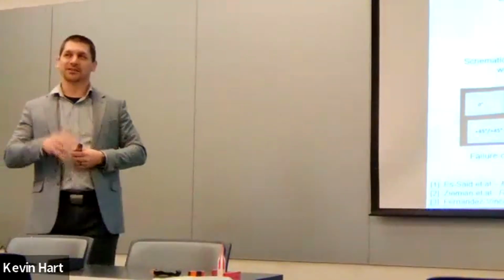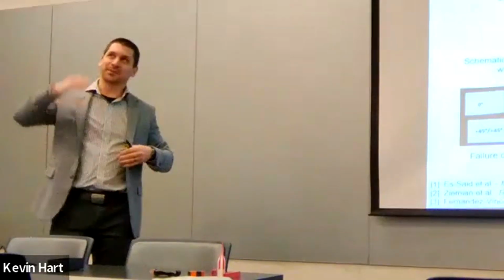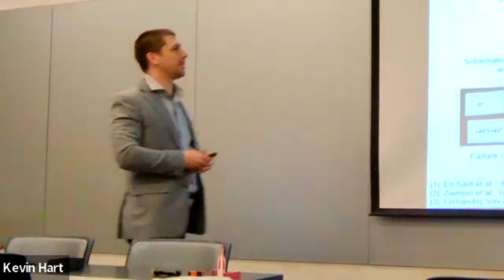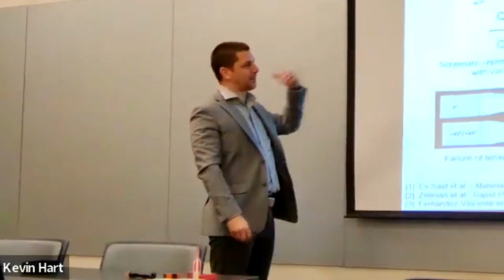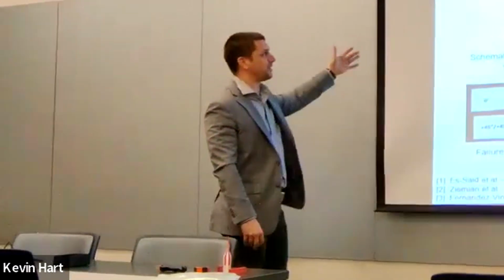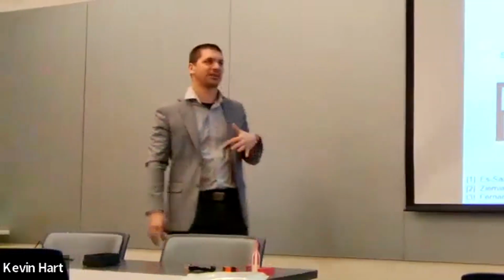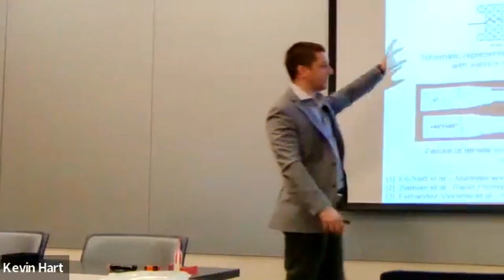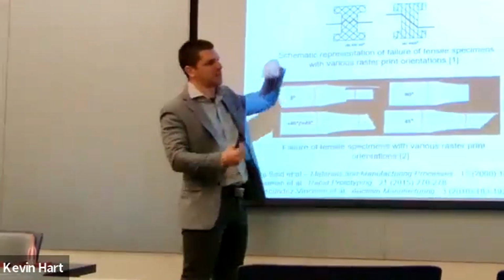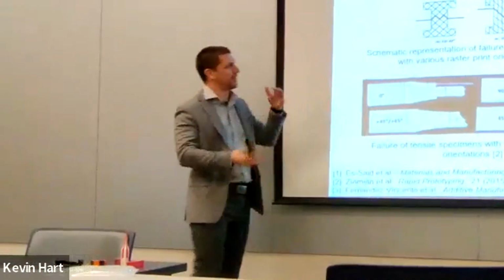But 3D printed objects are not often used in engineering applications, and mostly because they have a really weak interlayer strength, right? So if you're printing something layer by layer by layer, you tend to have a very weak interface between those layers of the print. A lot of people have demonstrated this in a lot of different ways, whether it's tension tests, flexure tests, compressive tests. We're showing that a little bit here: no matter how you orient a typical dog bone, it's going to fail at the interface between those weld lines of the 3D print.